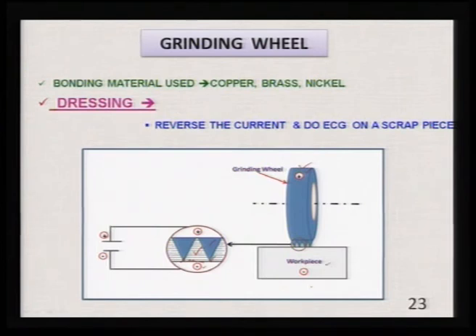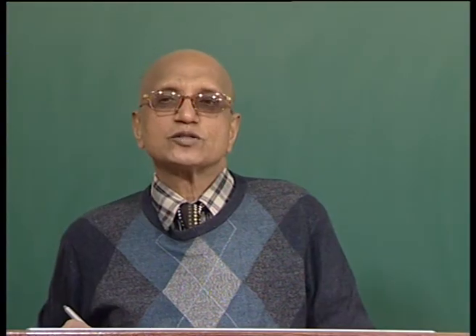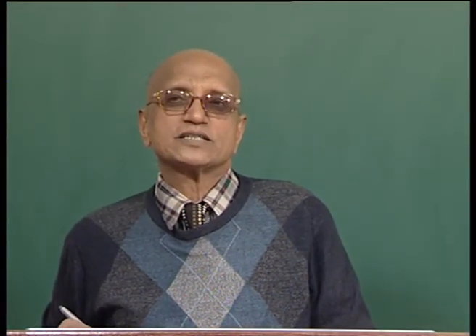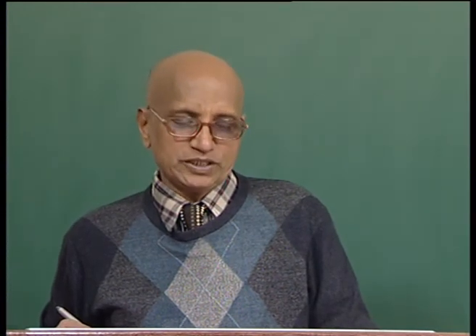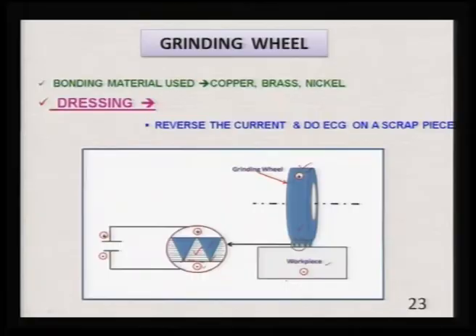Now, material is removed from the anode. So, in this particular case material will be removed from the grinding wheel, which is made the anode. As a result, what will happen? Whatever material was deposited on the grinding wheel due to clogging, or you want to remove material from the grinding wheel to allow fresh particles to project for the grinding operation, that material is dissolved from the grinding wheel, and once material is dissolved, fresh abrasive particles come outside or project outside the grinding wheel, and they